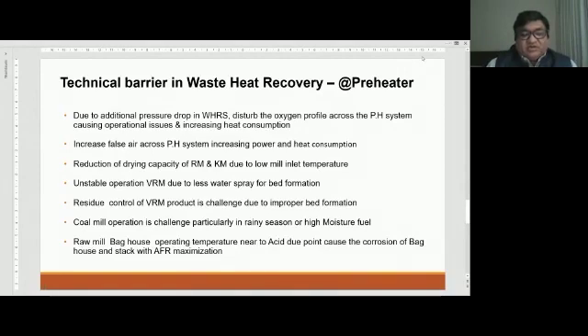The most important point I would also like to say to the industry, and this is my personal opinion and personal observation: the cement plants have gone to WHR quite significantly, but sometimes, whenever you're using alternative fuels or alternative raw materials that are sources of chlorine, sulfur and other volatile matters, at that point, if you do not maintain the temperature at your bag house as well as your stack and the raw mill circuit, you might face some corrosion problems because of the acidic dew point, because the addition of volatile matters, sulfur and chlorine becomes very critical.